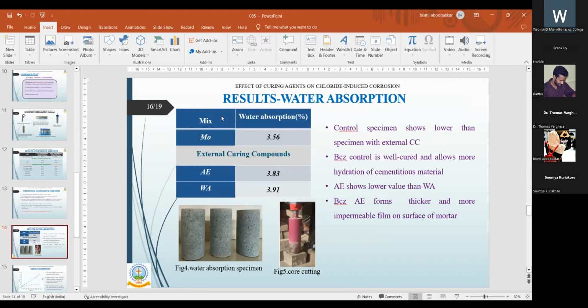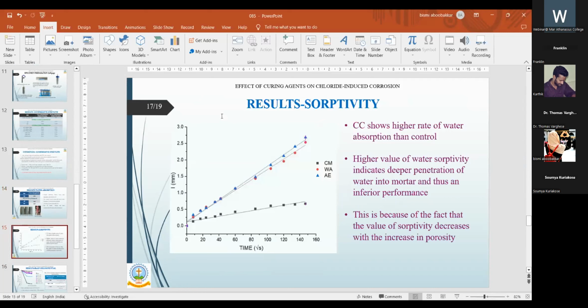These are the results of water absorption. From this, the control specimen shows a lower value than the specimen with the external curing compound, because the water-cured, well-cured specimen allows more hydration of cementitious material. And AE shows a lower value than the water-based curing compound because AE forms a thicker and more impermeable film on the surface of the mortar.